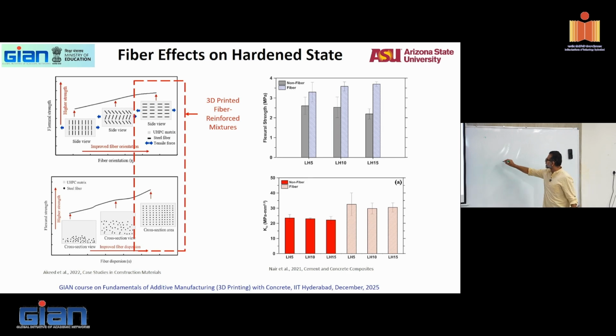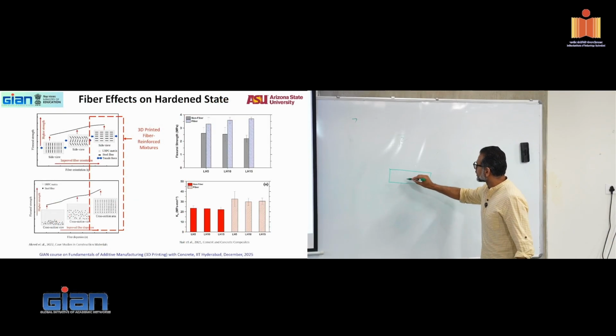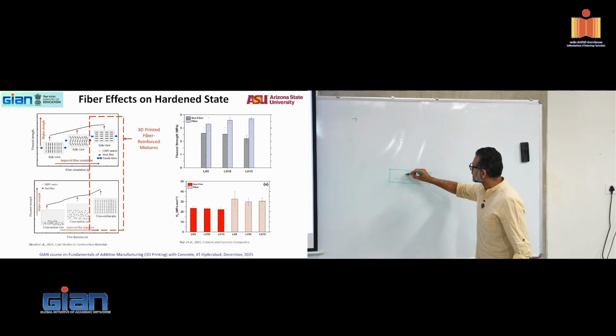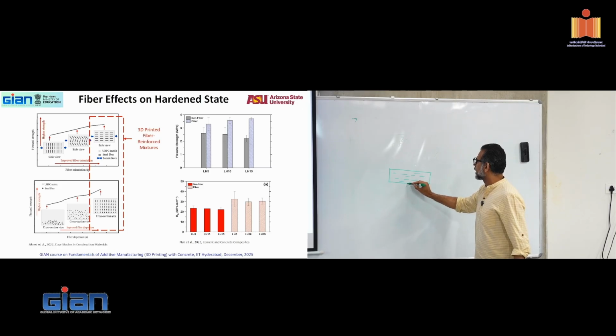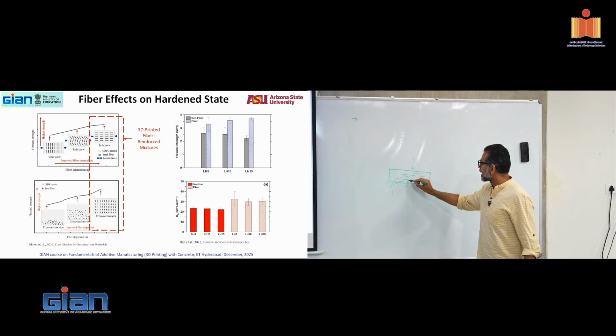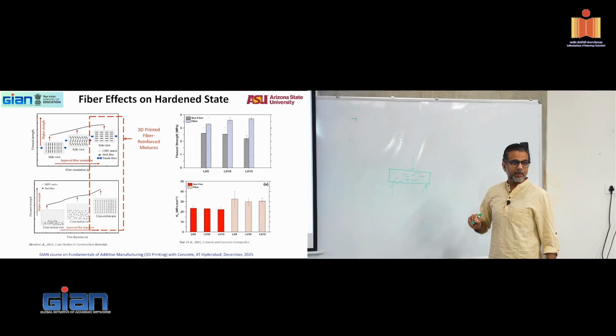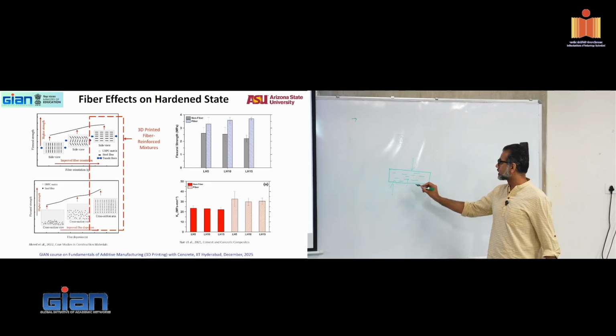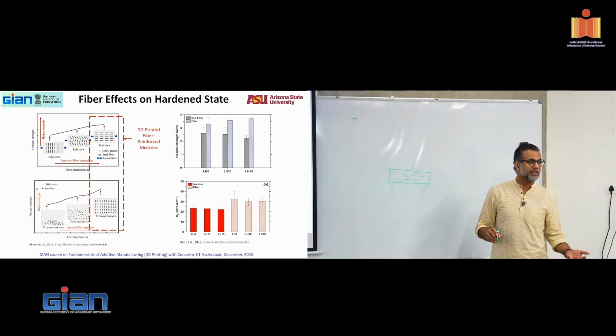So again, for flexure, if you have a beam that you're testing in flexure, and if your fibers are all aligned in this direction, a crack that is going in this direction will find a fiber, and you'll find all the effects associated with fibers, crack bridging, crack deflection, all of that, and therefore the toughness will increase, the flexural strength will increase.